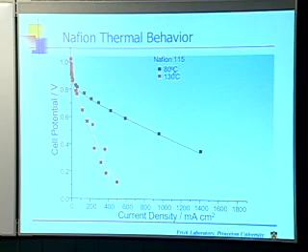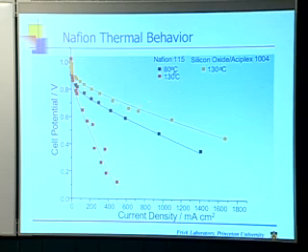And as you'll recall from last time, in our lab we're interested in running these devices at higher temperature to get around some of the issues that I mentioned, namely CO poisoning, water management, and thermal management. And when one does that, a normal Nafion-based MEA degrades, as I showed you last hour, but we do some material science, and we put a new membrane material in, which is the same Nafion, but now we've added a metal oxide component, typically about 3% by mass.